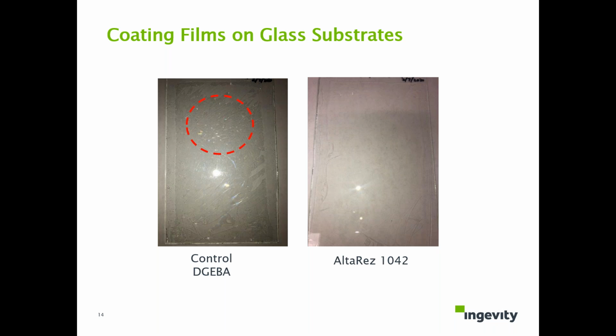So this is a coating film on glass panels. On the left-hand side is the benchmark bisphenol epoxy control. You can see that after post-cure it has some cracking in the surface. The right-hand side is our AltaRez epoxy. It's a very smooth, glossy, transparent coating film.